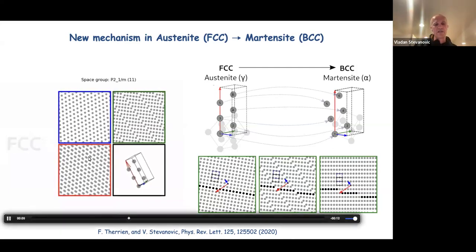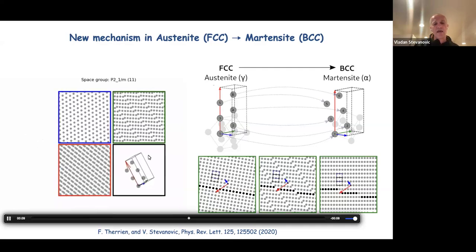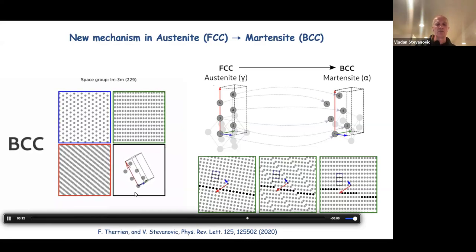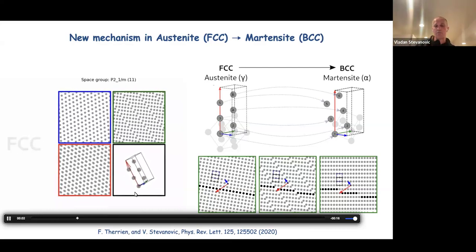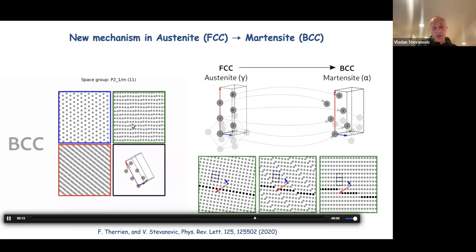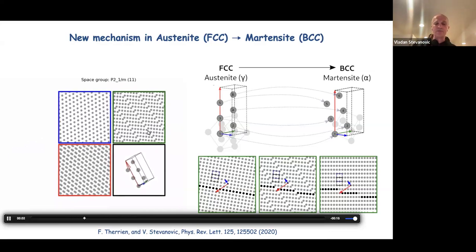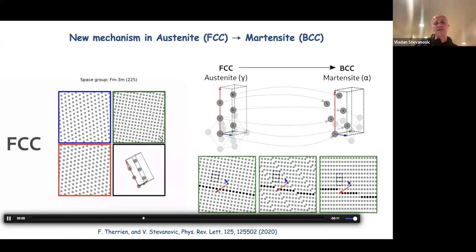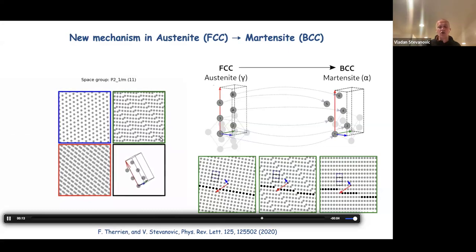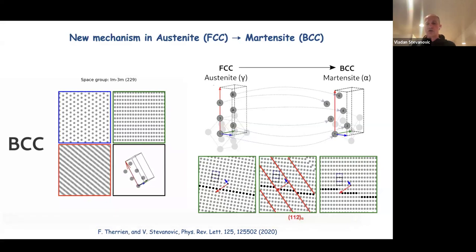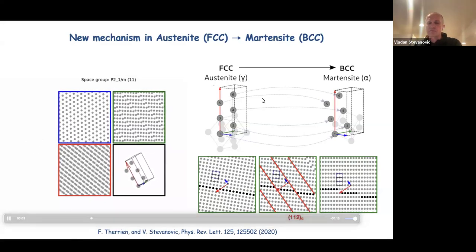that shows this transformation from FCC to BCC in the left panel from different angles. And this is the periodic box, or the scale of that transformation, that we find. So it's much bigger than the Bain mechanism that was proposed by Bain before. And if you look at the top right panel, what you find is this slipping process that happens. So there are slabs within which the Bain mechanism was actually found, but then the slabs slip between each other. And that slipping mechanism basically is a product of abandoning periodic boundary conditions, then minimizing the global strain.